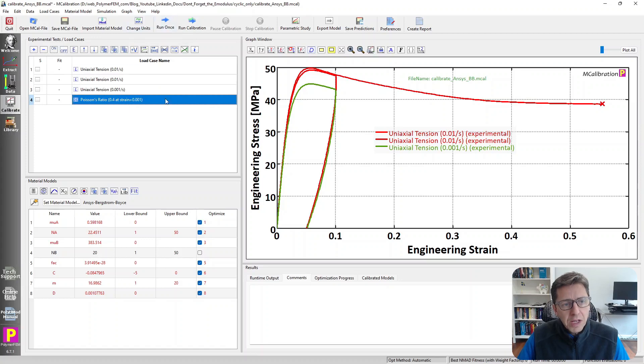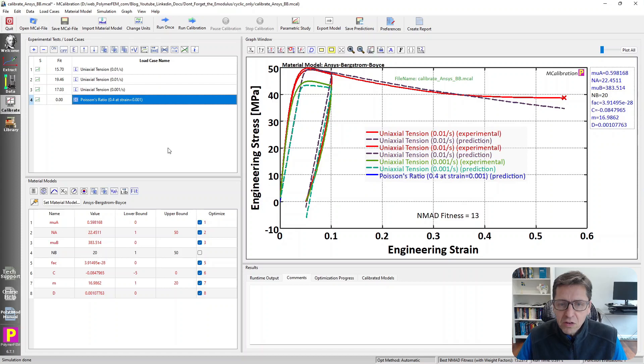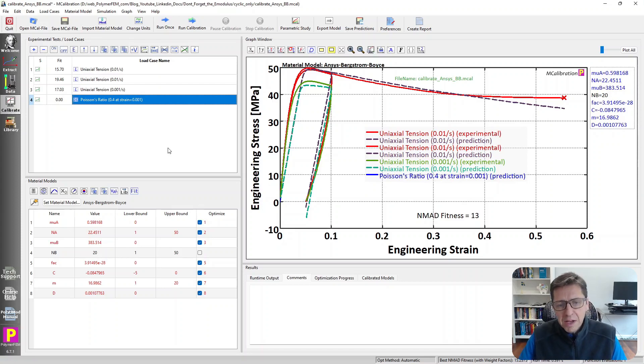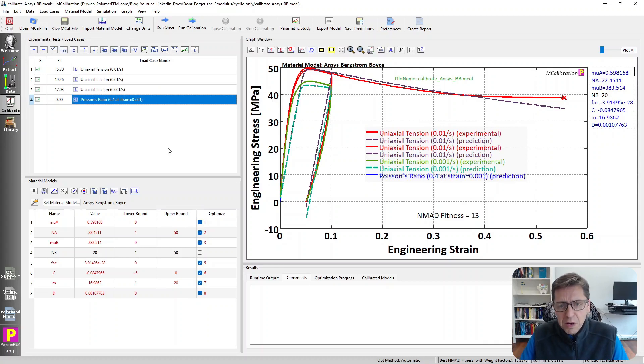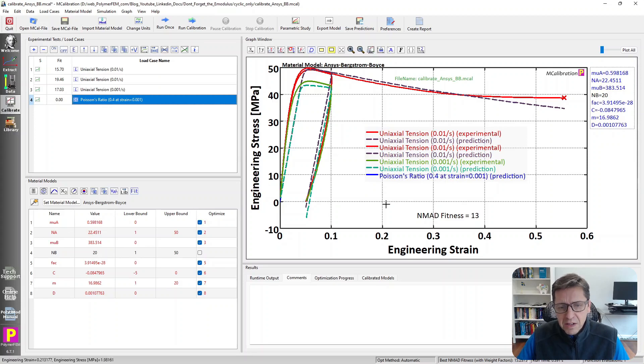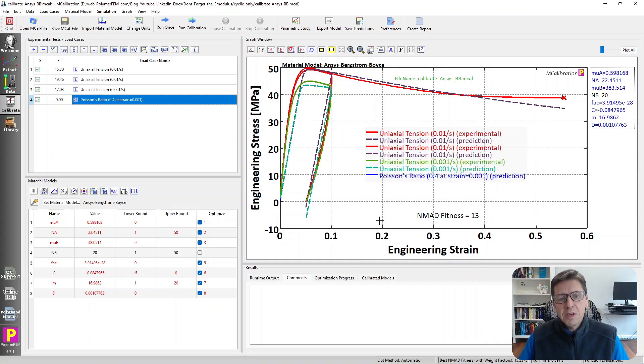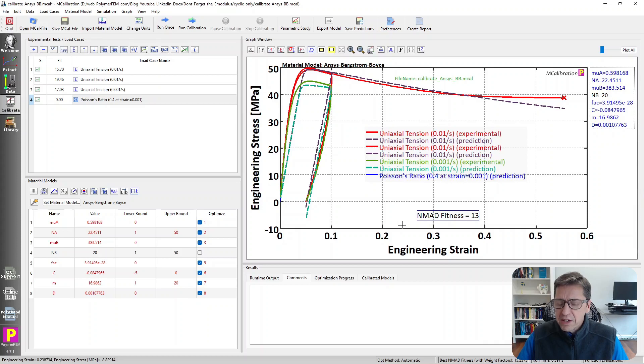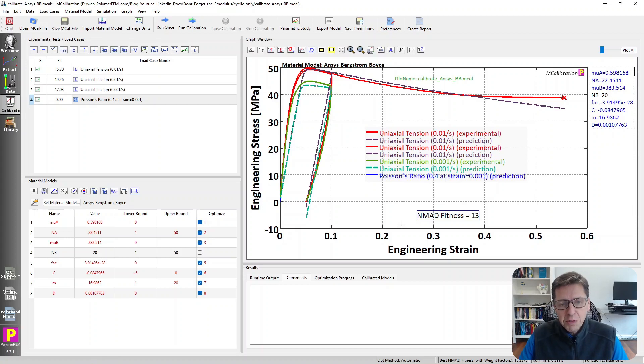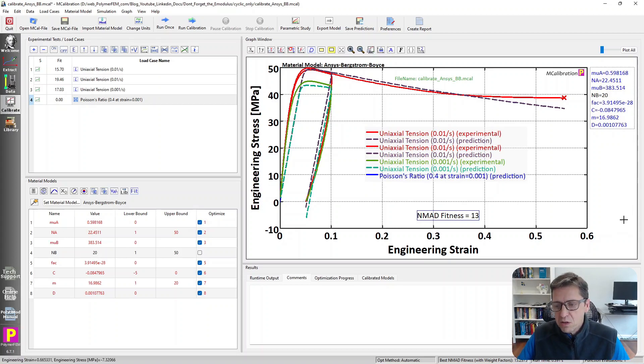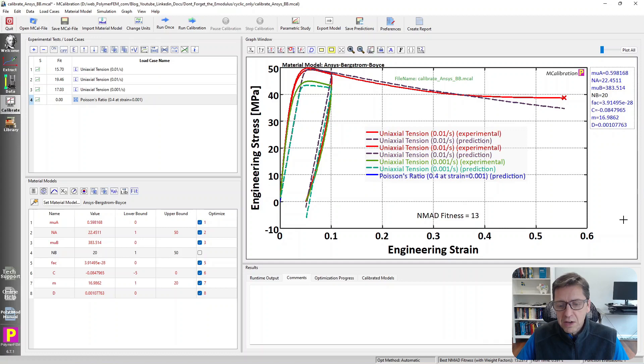So here's the calibration results. I'm going to run this once. And this is the ANSYS-Bergstrom-Boyce model, and I've talked about this in the past. It's not always the best material model for thermoplastic material, but it's a suitable material model for this demonstration. So then the key here is the dash lines are the predictions from this Bergstrom-Boyce material model. It's a viscoplastic material model. And the error here, the average error of the predictions is 13%, which is not so bad. I mean, I often try to aim for about 10% errors in my finite element simulation. So here it is, a calibration. We have loading and unloading, multiple strain rates. We get an error of 13%.